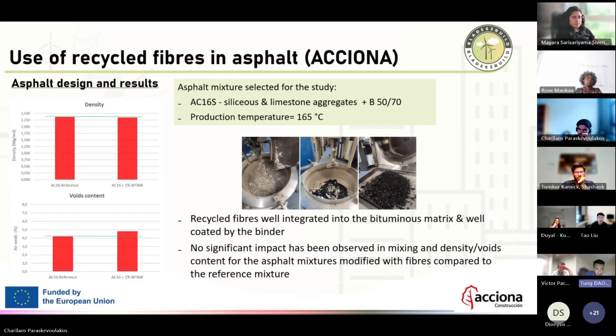behavior, we didn't see any difference in terms of density between the ordinary asphalt and the asphalt with 1% of wind turbine blade waste. In terms of void content, we have a little bit higher, but it's not like the concrete, because in concrete we don't like the voids. In the asphalt we like the voids because the void is there to accommodate the volume change due to the thermal gradient between the seasons, to be sure that the bitumen can find the place when it is melted by the increase of the temperature.